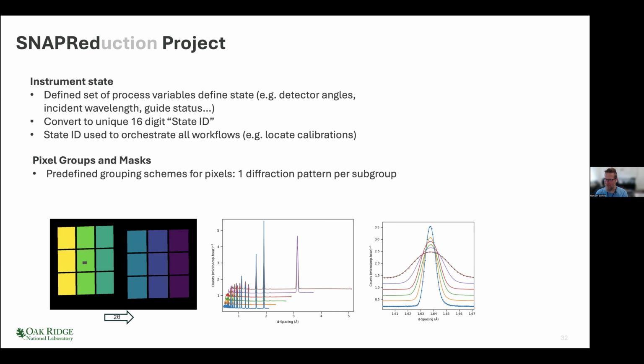And so you immediately see the complexity because the individual groups are at different angles. My d-spacing range is completely different for each one of those. And this image on the right here shows a zoom in to the peak, and you can see the resolution is also changing. And a tiny detail I'll emphasize, because it cost me maybe about 4 months of my life, is the software is automatically selecting the appropriate binning. So the spectra where the peaks are broader, the histogram bins are wider apart. And that means whichever Bragg peak you're looking at, it's being sampled with the same resolution. And that's important for doing Rietveld analysis.